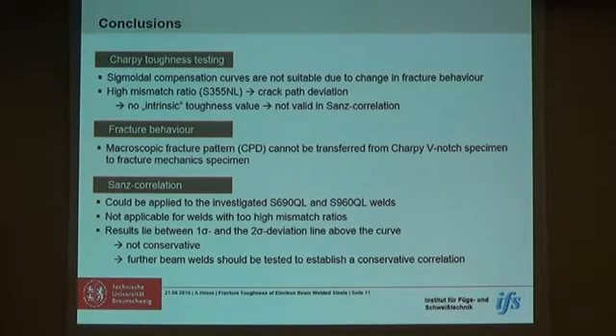To sum it up, we can say for the Charpy toughness test, that the sigmoidal compensation curves, which are usually used, aren't suitable due to the change in fracture behavior, and that the high mismatch ratio of the S355 welds led to crack path deviation even at relatively low temperatures, which means we couldn't find an intrinsic toughness value with the help of the Charpy toughness tests, and we couldn't use it in the Sanz correlation. The fracture behavior showed us that the macroscopic fracture pattern, if we speak about crack path deviation, cannot be transferred from the Charpy V0 specimen to fracture mechanics specimen.